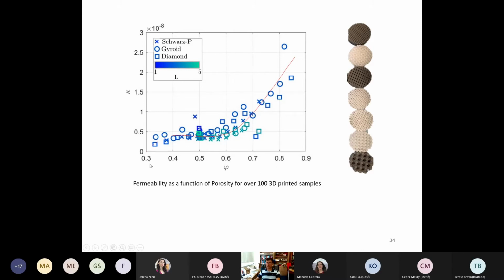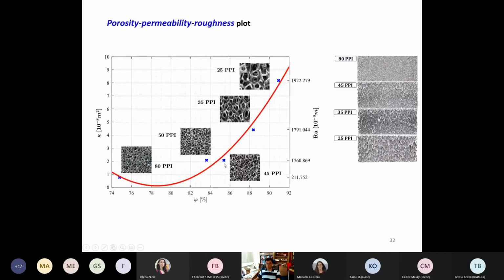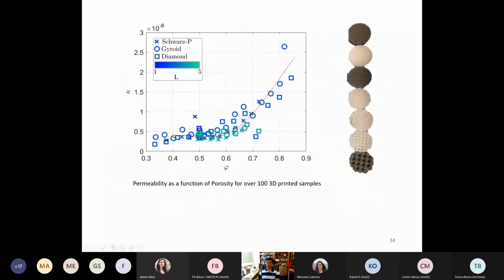The porosity here is changing from 30% to 90%, and the permeability range is also quite large. The interesting thing that we did not see in the previous measurement, but now see in this one, is that you can clearly see two areas. At low porosities between 30% and 60%, it doesn't seem to matter much how much the porosity is. You have a constant sort of permeability that you can get, and then after that, for higher porosity, you have a linear behavior between porosity and permeability, and that's the line.